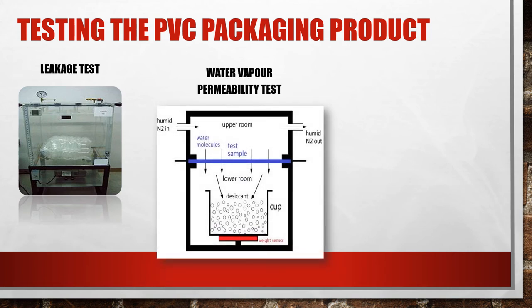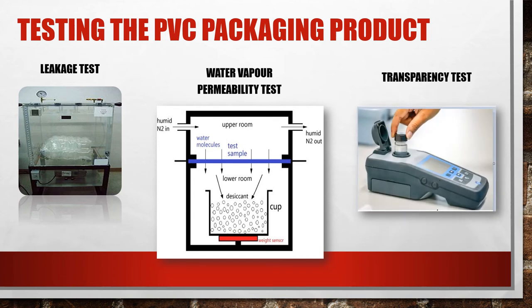Water Vapor Permeability Test. Fill 5 containers with nominal volume of water and heat seal the PVC container with an aluminium foil polyethylene laminate or other suitable seal. Weigh accurately each container and allow to stand for 14 days at a relative humidity of 60 ± 5% and temperature between 20 and 25 degrees Celsius. Reweigh the container. The loss in each container should not be more than 0.2%. Transparency Test: Fill 5 empty containers to their nominal capacity with diluted suspension. The cloudiness of the diluted suspension in each container should be detectable when viewed through the containers, as compared with a container of the same type filled with water.